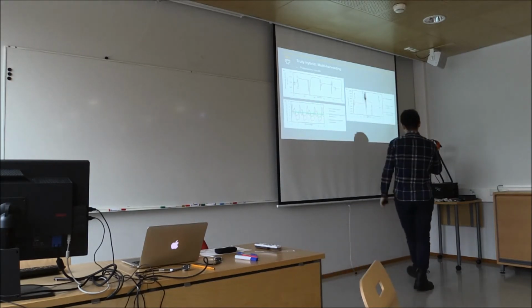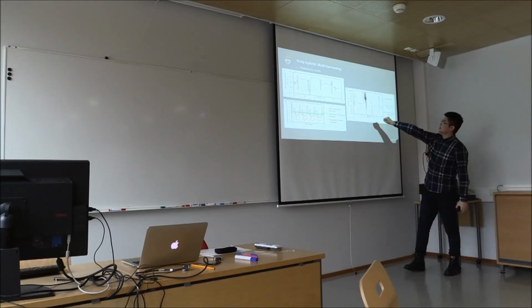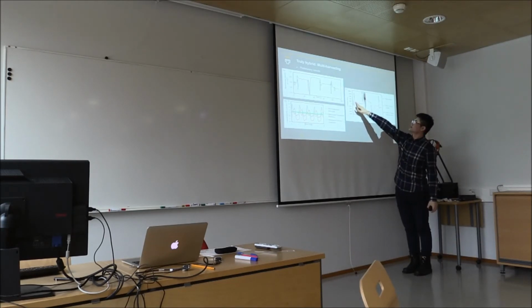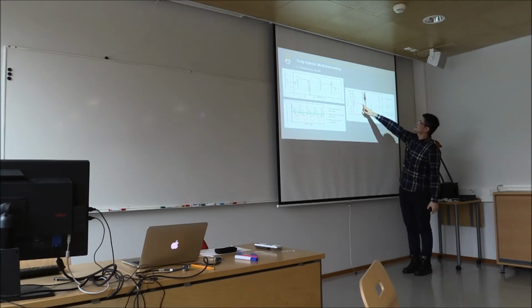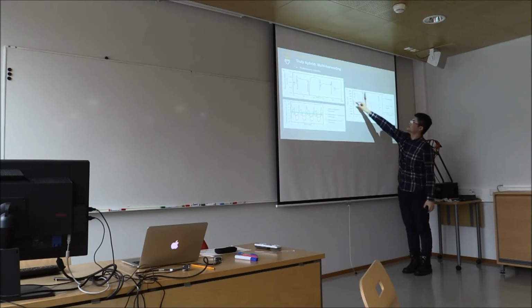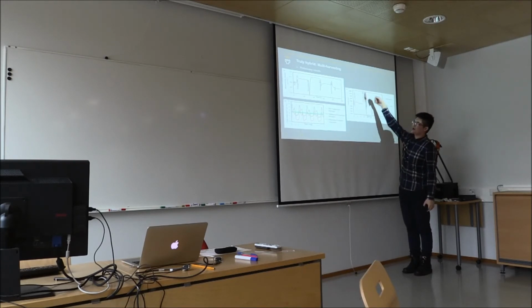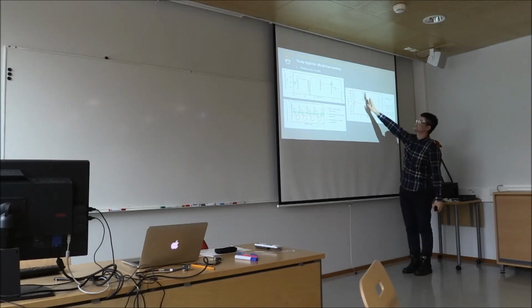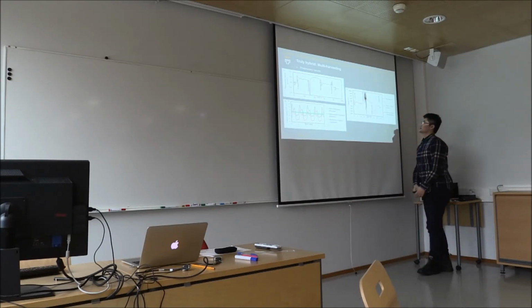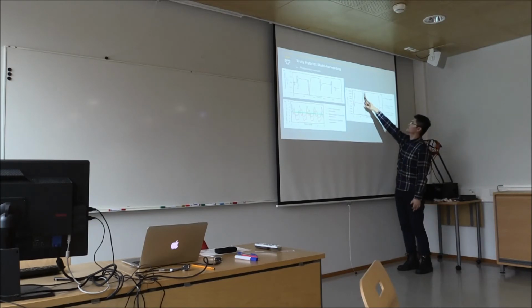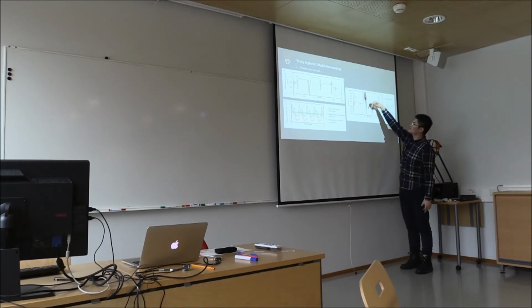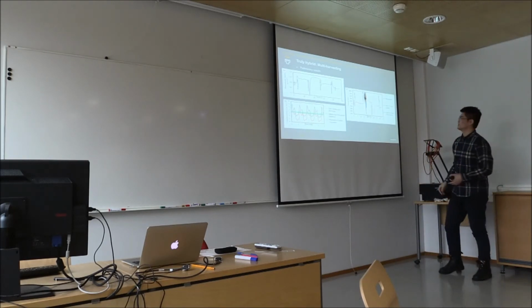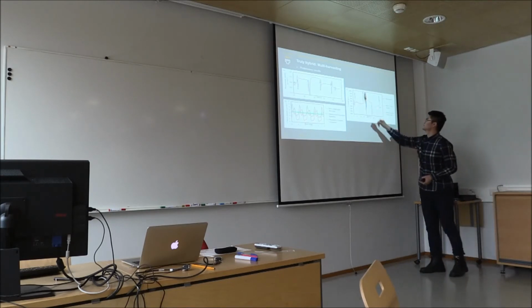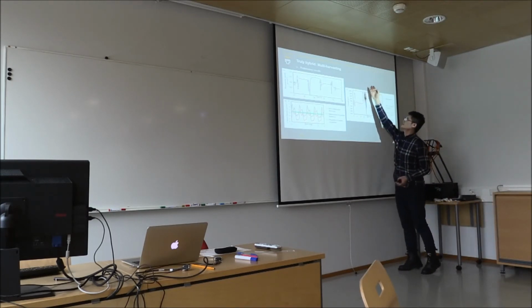And also, if we have a look at all three energy responses: from the dark we have this. If we have a white light, it generates some level of energy. And also if we have some heat in, it will generate another level of energy, which is the add-on of these two energies. And also we impact the material to add some mechanical energy. It will generate this piezoelectric response without any compromise or sacrifice of this total energy. So the highest energy can go here. The downside is just because it's an AC signal, we didn't rectify it, so it goes here. But you can see the highest level is actually larger than here.